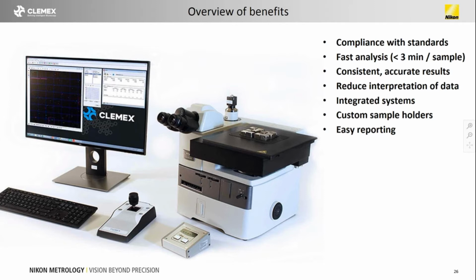So the advantage of using an automated inclusion rating system and the Clemex CIR system is that we comply with many standards. As we saw, we just looked at ASTM and ISO. We have fast analysis, so it takes less than 3 minutes for an ISO standard to be analyzed. This is 200 square millimeters. We get consistent and accurate results because of the precision of an auto stage and our software, which in turn reduces the interpretation of data. An operator can interpret data differently from one to another, so you can get different data. That's not the case for CIR.